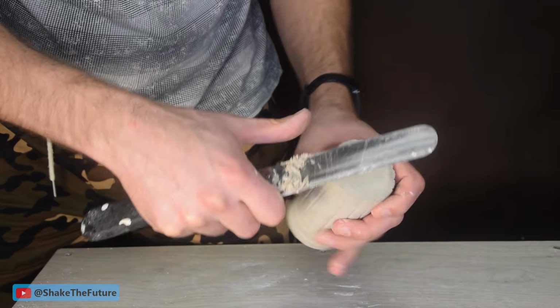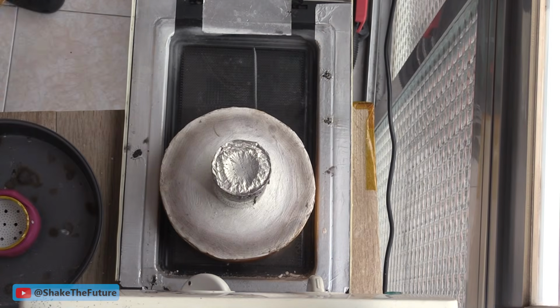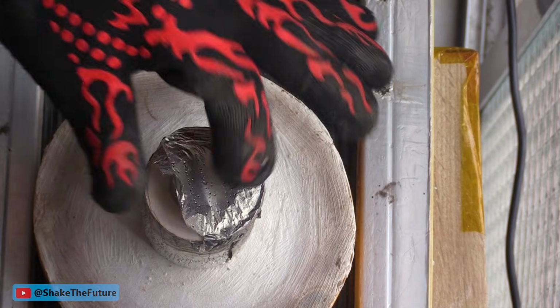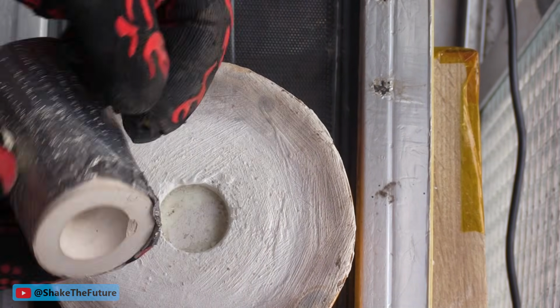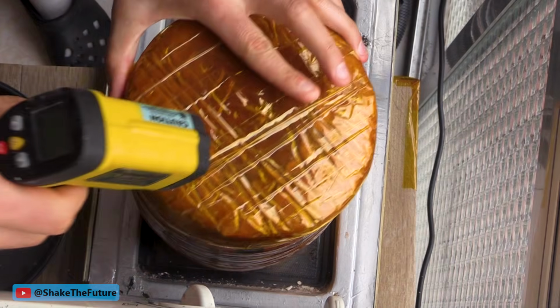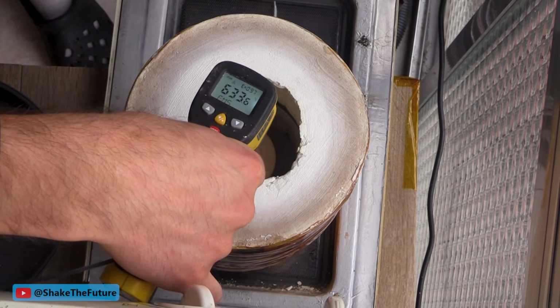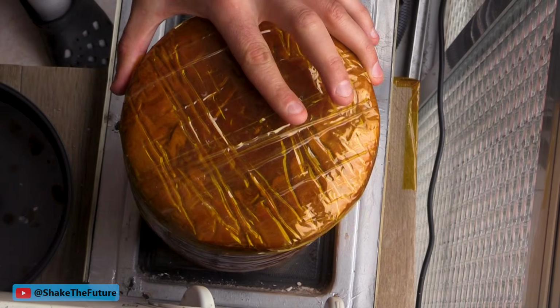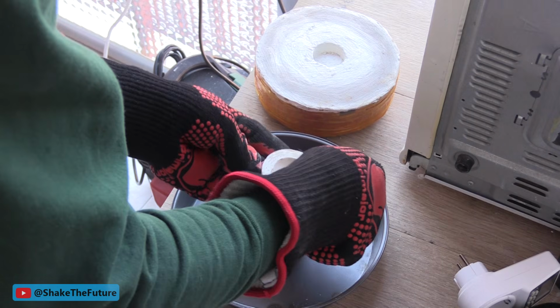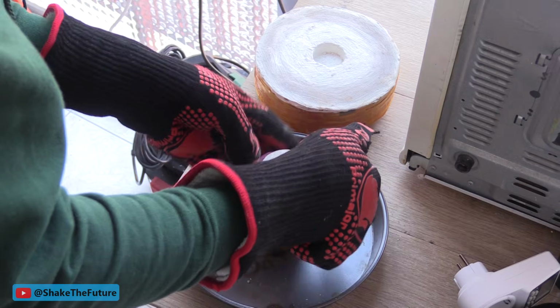After drying the mold in an air fryer, I heated it up until the foil started to melt or crumble. It's a good indicator that the mold has reached at least 500 degrees Celsius. And I kept heating it up until it reached 600 degrees Celsius. I'm gonna cast the ring in copper.